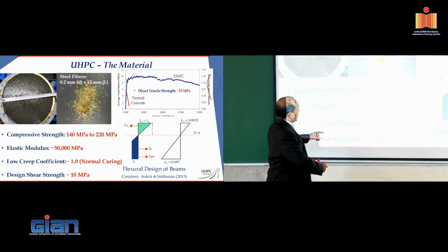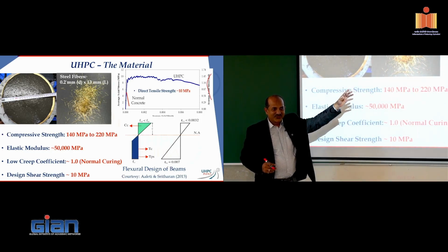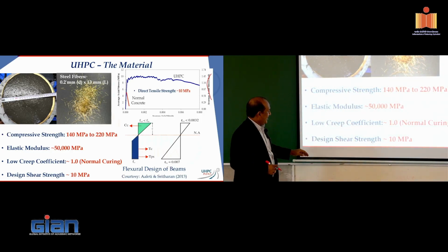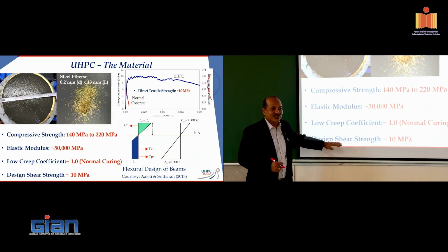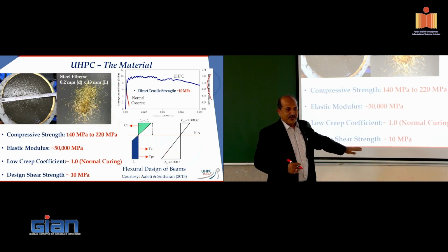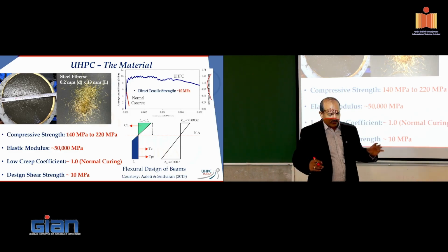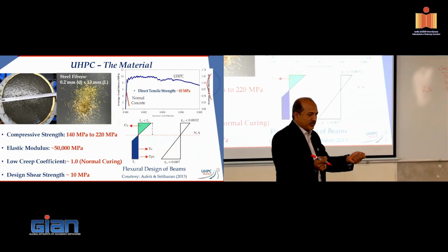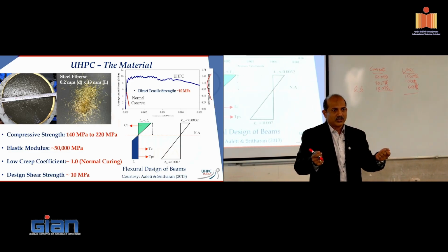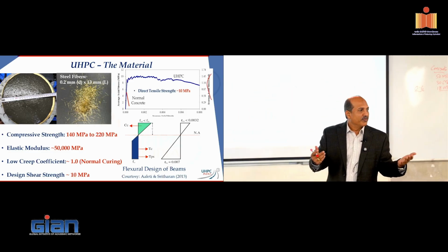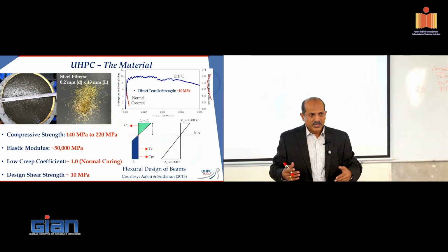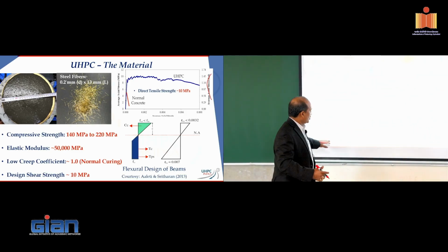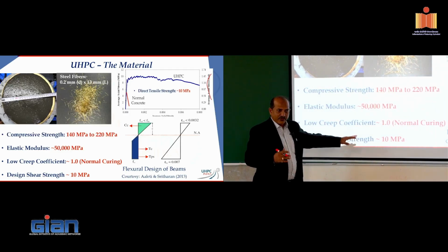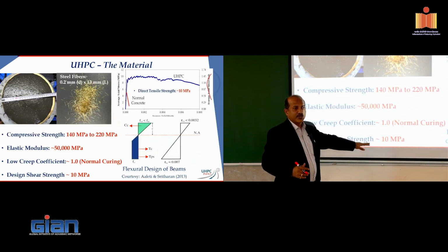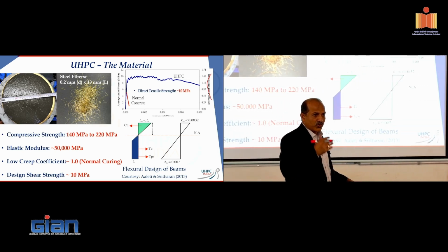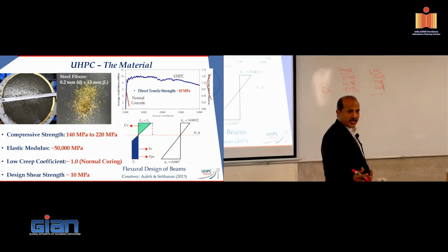And the same strain hardening behavior that you see right at the top over there, it helps in improving the shear behavior tremendously. And even without rebar. Now, you look at your concrete code and concrete plus rebar, your tau c max is about 4 MPa. Right? But here, if you look at it, just your design shear strength out of UHPC, the fibrous UHPC, is right at about 10 MPa. So you can have more going for it, but you can get 2.5, 3 times the shear capacity out of that.